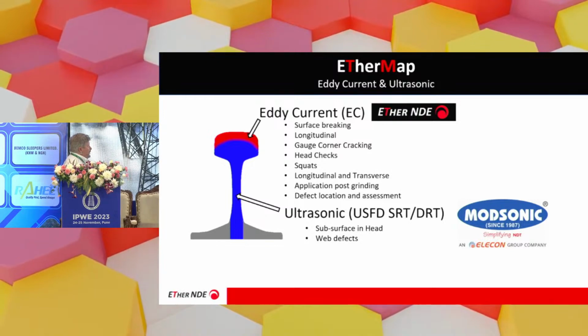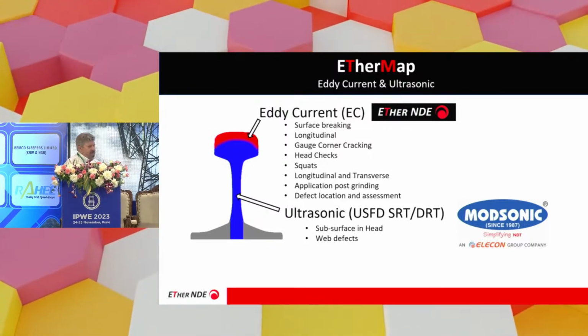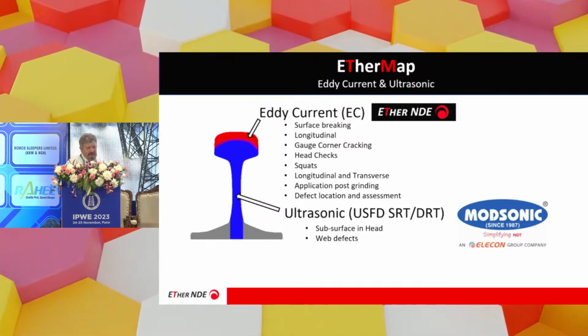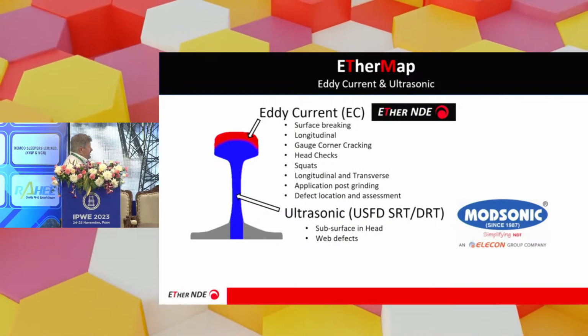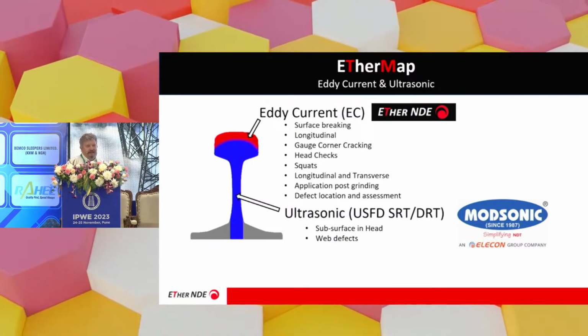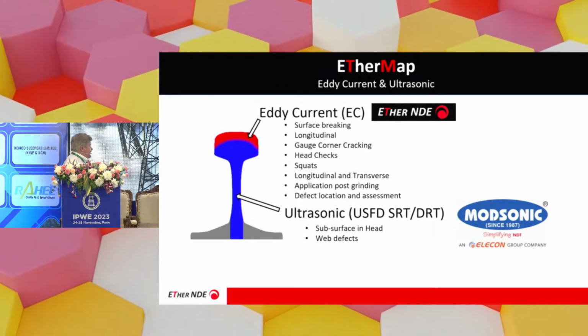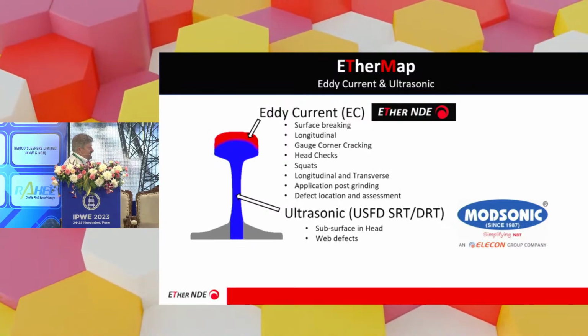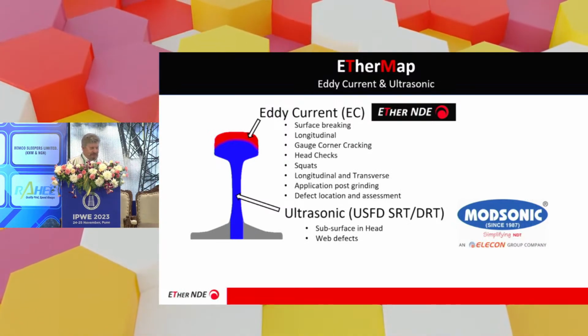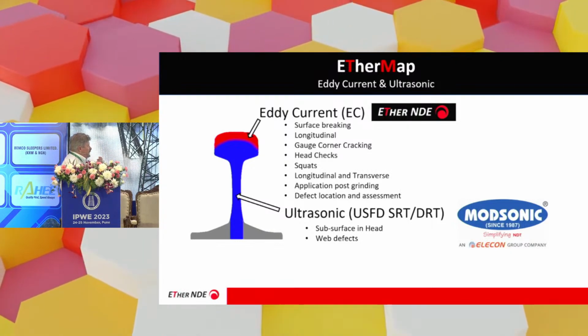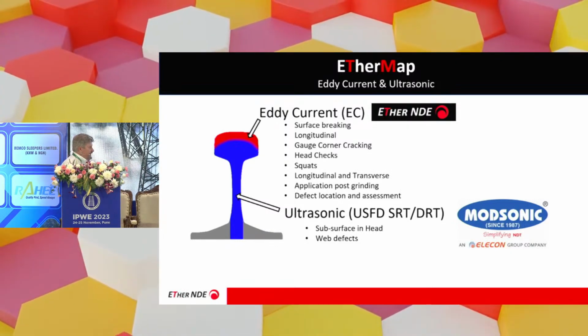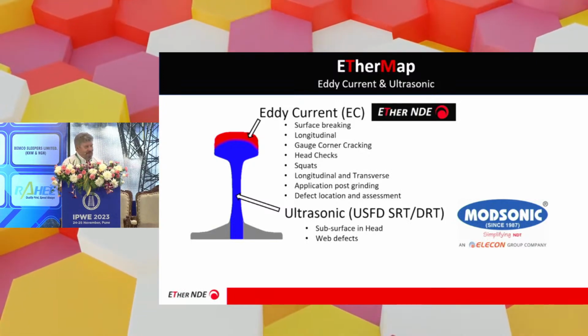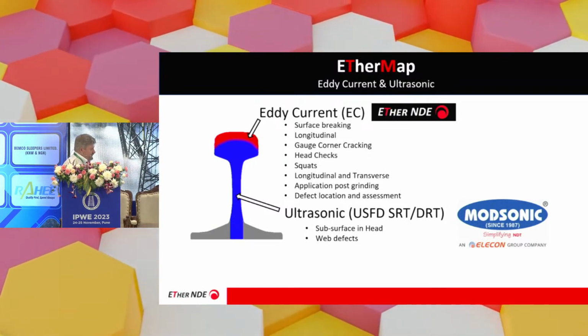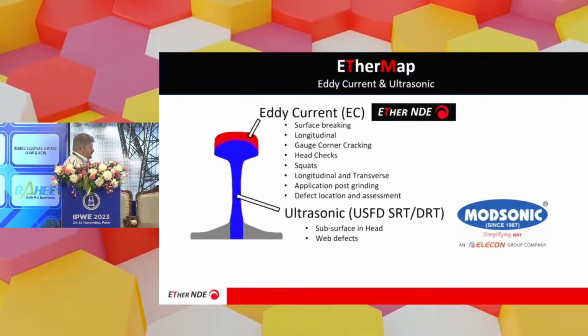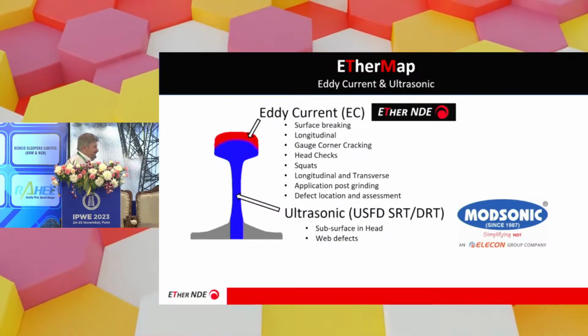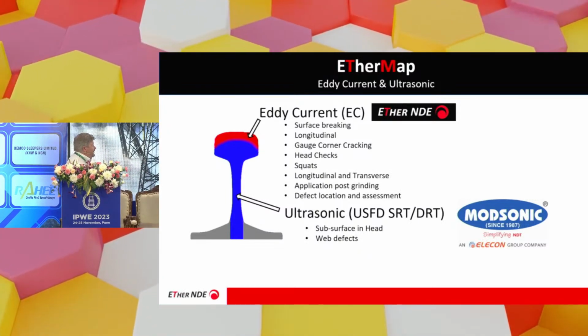One interesting application is that this could be used to find defects in an in-service rail. But also, if you grind the track, mainly to remove cracks and other defects, you actually disguise the fact that there are defects there because of the surface texture. We can run this behind the grinding train and find defects. So I think it can be used in conjunction with UT to make the UT better, but in its own right it has some reason for existence.